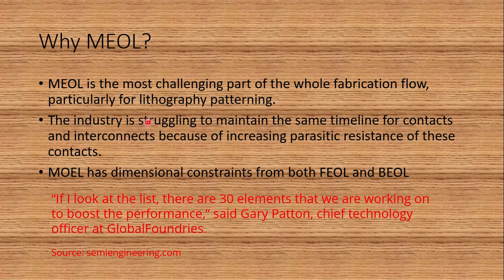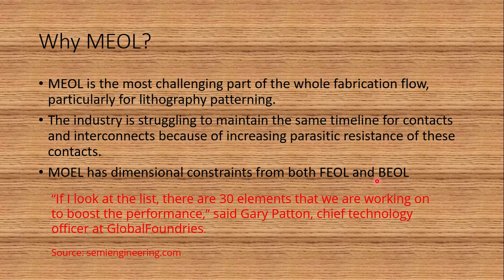Today MEOL is the most challenging part of the whole fabrication flow, particularly for lithography patterning. The industry is struggling to maintain the same timeline for contacts and interconnects because of increasing parasitic resistance as device size scales down. The interconnect size must also become thinner, which impacts the contacts. MEOL has dimensional constraints from both FEOL and BEOL — FEOL is reducing in size, while BEOL copper interconnects see rising resistance as thickness reduces.